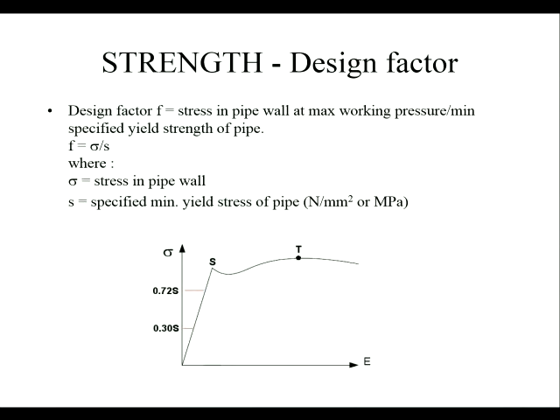So we usually have what's called a design factor included in our equation. So the design factor that I use is the stress in the pipe wall at the maximum working pressure divided by the minimum specified yield strength of the pipe. So the minimum specified yield strength is a measured value. It's not an average value, it's the minimum value that you would get from your tests. And that's very important because we don't want things to fail. So we don't want to use an average value where the chances are things will be smaller than that. We want to use the minimum value.